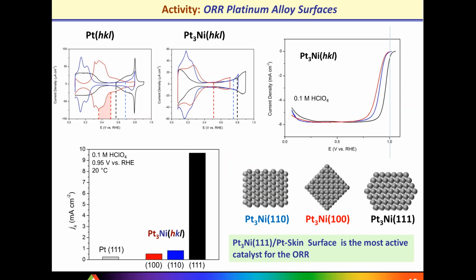And what was extremely appealing is that we were extremely eager to learn how all of those surfaces with the very same surface composition as pure platinum single crystals, however different bulk composition, behave. And here you can see a comparison between pure platinum and platinum nickel single crystals. When you do those kinds of comparisons, you're looking into three curves, it's very difficult to see one-on-one. But the message from this slide is that the platinum nickel 111 skin was one order of magnitude more active than any of those pure platinum surfaces. And if we express that relative to state-of-the-art platinum carbon catalyst, the factor of improvement is almost 2 orders of magnitude.